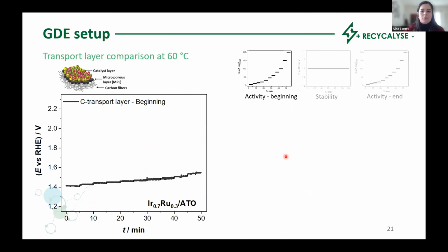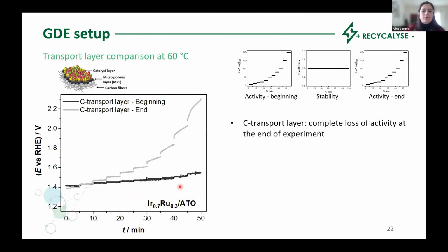So let's start the comparison with the carbon-based transport layer. And here you can see its beginning activity, which is not too bad for a catalyst. Then if we go through the entire protocol, we can see that the gray curves are not in line with the black ones, and that they are reaching high potential fast, which means that the catalyst has degraded during the stability step, as higher potential for the same currents is an indication of a badly performing catalyst. So this is actually expected from the previous results. The catalyst on the carbon transport layer completely lost its activity at the end of the experiment.